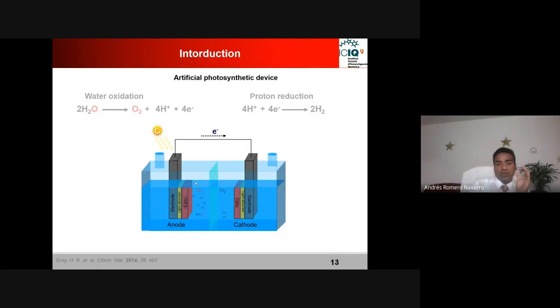So what we can do is have a device, and in one electrode called the anode, we can do this oxidation of water to get molecular oxygen. And then we can have a cathode material where the generated proton can be reduced to hydrogen, by taking the electron from the anode side to the cathode. So that perfectly mimics the natural photosystem. That is photosystem 2, that is the electron carrier, and this cathode side is basically photosystem 1. So that is one part.